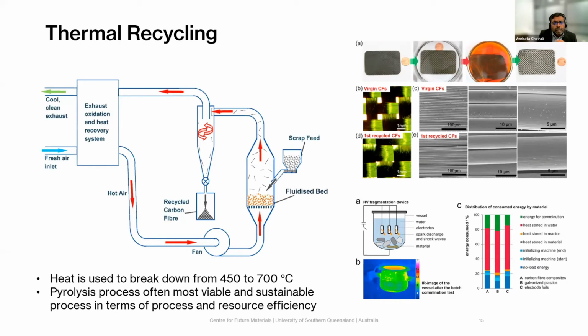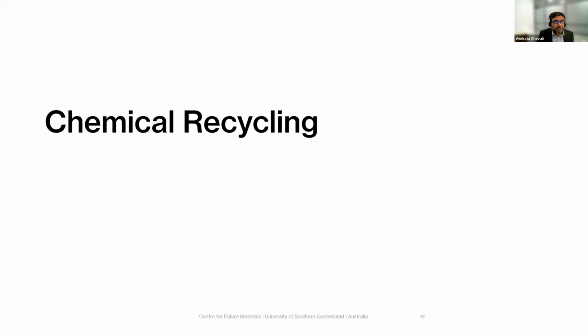And within this, you can also do a combination of high voltage fragmentation and other types of processes as well. And with a high amount of success, you can achieve very clean fibers from thermal recycling, because with the application of heat, the resin completely decomposes, and at that stage, you just have to wash off anything that is remaining on the fibers. Pyrolysis often is the most viable and sustainable process in terms of the thermal recycling methods. However, it has its own cons as well, as we see in a minute.